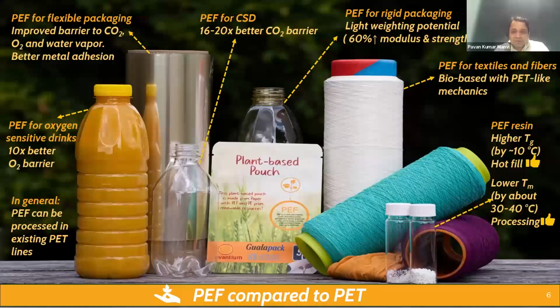And then a very short overview of where PEF has already been implemented and what the value propositions are. If we look at the packaging section, PEF has much better oxygen and carbon dioxide barrier properties, even though it is processed on the existing PET lines in a similar process, and we can get better properties. For packaging, it is quite important how the barrier properties are. So PEF has 10 times better oxygen barrier properties, much better water vapor properties, and 16 to 20 times better carbon dioxide barrier properties.